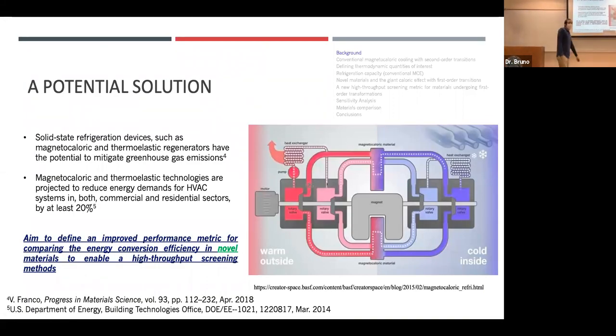So one potential solution to replace, I'm not saying it's the absolute solution, but a potential solution, would be solid state refrigeration through something called the magnetocaloric effect. This is a diagram of a magnetocaloric refrigeration cycle, where we have a solid material in this block that is exposed to a magnetic field. It changes the thermodynamic state of the material and actually cools it off. Then when we remove and apply that magnetic field, the material gets hot or it gets cold, and we can flow some thermal transport fluid over the solid material and generate a gradient in the system. So we have a hot temperature reservoir and a cold temperature reservoir.